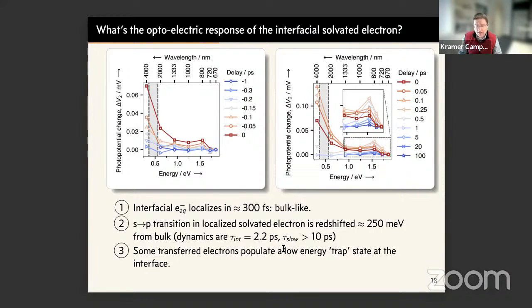This is bulk-like. At longer times, you still see this narrow feature at much higher photon energies, but it is clearly redshifted from bulk. So in bulk, this feature is at 720 nanometers, and our spectral resolution is not the greatest for practical reasons that we can discuss, but wherever the peak of this feature is, it's definitely at longer wavelengths than 720 nanometers. It is also true that you have intensity at 720 nanometers even at 0 picoseconds. So some electrons appear to localize almost immediately at time 0.